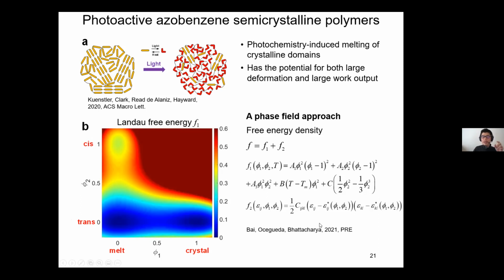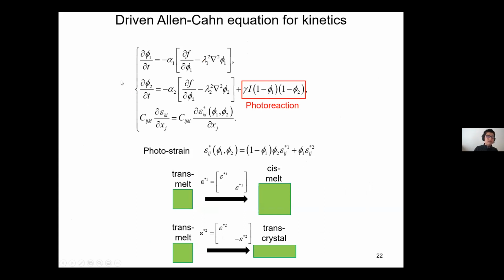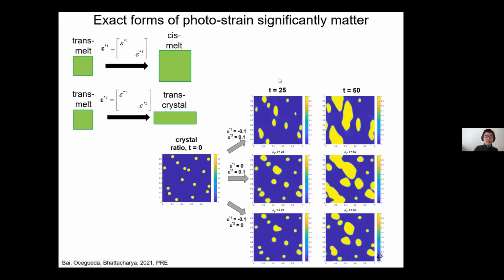I can also introduce this long range elastic interaction as I did before, okay? Now I will skip this mathematical formula. Basically, we're using a driven Allen-Cahn equation, which is classical, but then we add a photoreaction part, which drives the system away from equilibrium. So that's still the idea. Now, I can have a little more sophisticated photo strain because I now have all different kinds of phases. Again, if I put it in the model, you can see that if I give different values of this photo strain, indeed, I will have different microstructures in my phase field result. So if we understood the previous section, this is nothing too much more special, right? We already knew this.